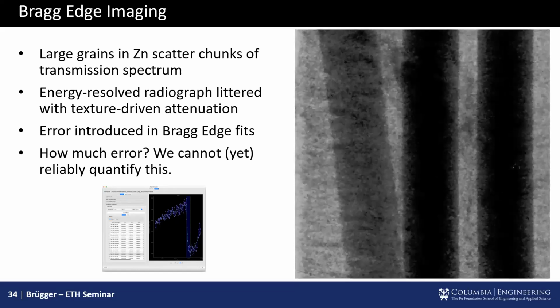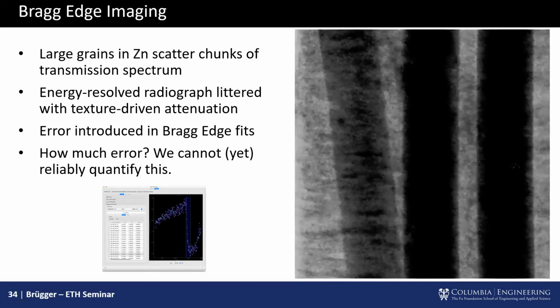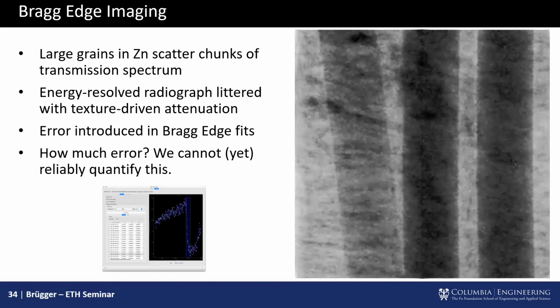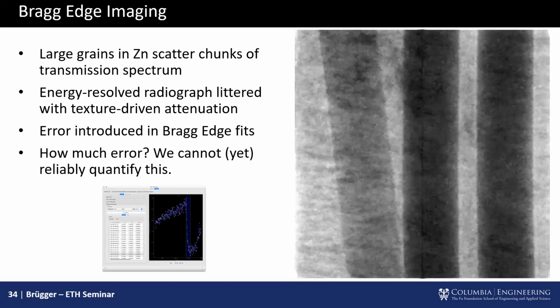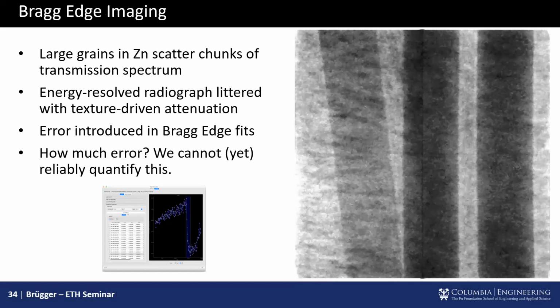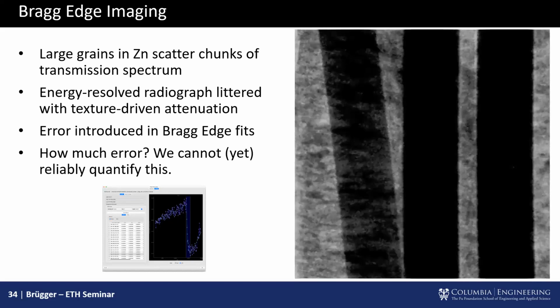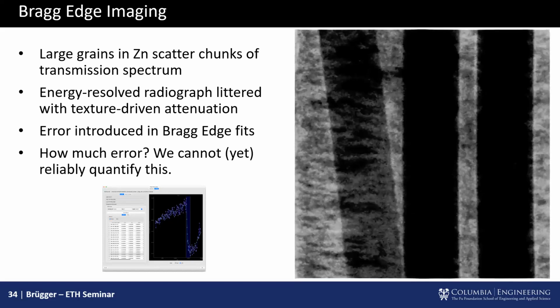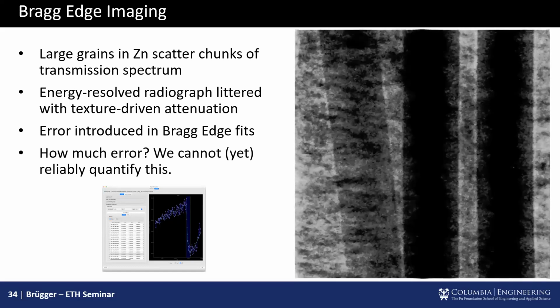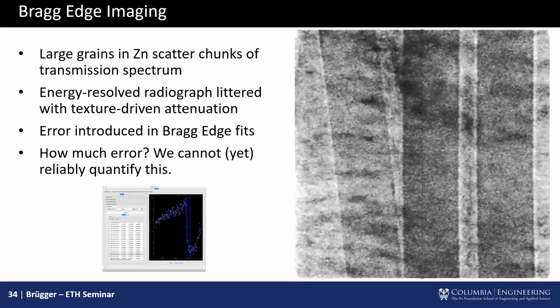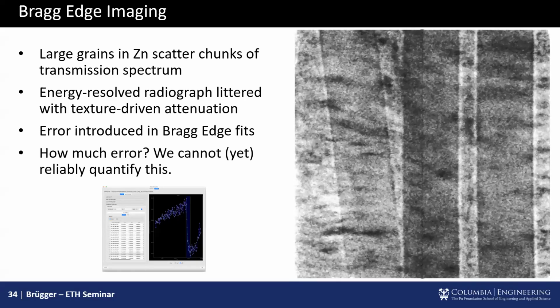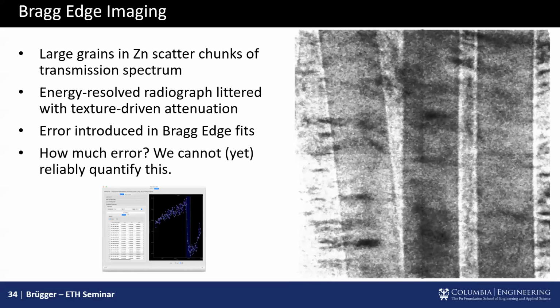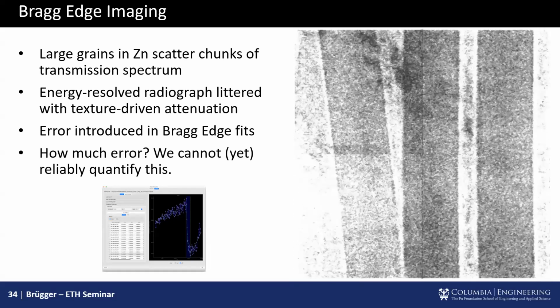Now, we also wanted to do Bragg edge imaging on this, but unfortunately, the zinc structure and the zinc crystals were so large, you can see them. There's sort of these black clouds that show up in this image. This is now rastering through the various frequencies of neutrons. So it's like looking at the different colors of light. Unfortunately, those made reading the residual stresses using Bragg edge imaging in this sample, I wouldn't say impossible, but at this point, very, very difficult. So what this means is that we'll actually go back and do traditional just point-to-point diffraction to understand this.